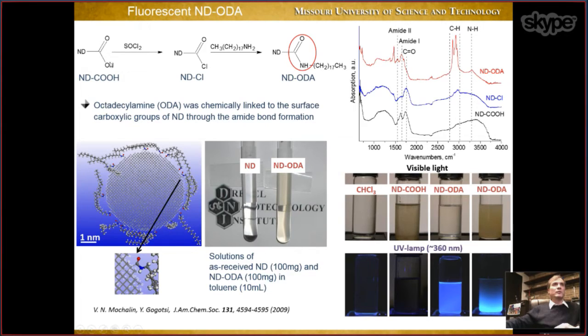Okay, compare this to this. This is hydrophilic. It has carboxylic groups. So when you disperse this hydrophilic material in toluene, which is shown here, it precipitates immediately. It doesn't like toluene. Toluene is a hydrophobic solvent. This is hydrophilic material, so it doesn't disperse well. When you attach this long hydrocarbon chain, it disperses much better.